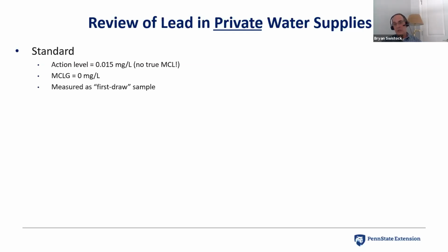There is a goal of 0 milligrams per liter, recognizing that lead can only do bad things. It has no good use in your body. And so any amount of lead can be damaging. And in fact, even levels as low as 1 part per billion can be a problem for very young infants. It is measured uniquely in what's called a first draw sample, where we measure water that has been sitting in the plumbing for several hours, usually overnight, to try to get at that worst case scenario of how much lead builds up from plumbing system corrosion. So it's unique. That and copper, lead and copper both have a first draw sample, which is different than pretty much everything else that we collect for water quality, where we typically would get a running water sample.